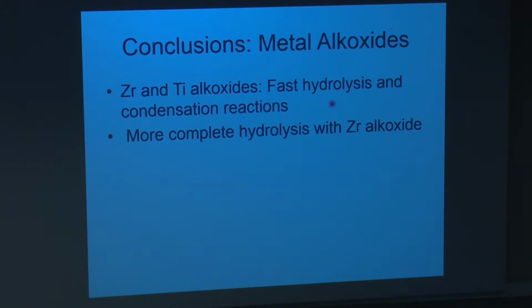So the conclusion from this work is that, yes, we were able to look at the zirconium and titanium alkoxide reactions, although they were fast, using this rapid mixing flow-through technique. Also, if you look at the hydrolysis of zirconium relative to titanium, zirconium hydrolyzed much faster and more completely than the titanium alkoxide.